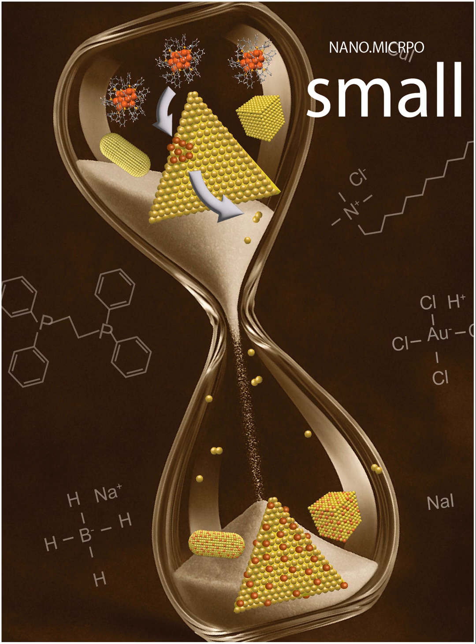That's impressive. But can they actually control how much copper goes in? Because 12% might be good for one thing, but maybe you need 30% for another application. Absolutely crucial point. And yes, that's another major win for this method. They found they could control the copper content just by changing how much of the Cu18 nanocluster solution they added at the start. Seriously, it's that simple, like adjusting a recipe. Pretty much. They saw a direct, almost linear relationship. Add more Cu18 solution, you get a higher percentage of copper in the final alloy triangles. At least up to about 60% copper, they showed this nice control.